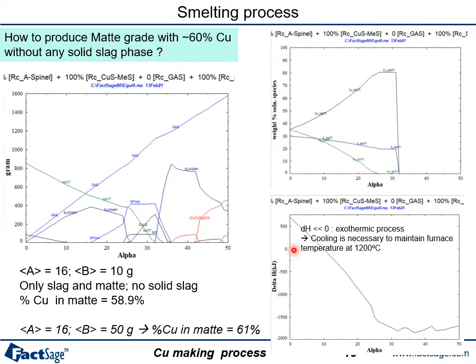So as you can see, this is 0, okay? So again, about this area, you'll have the endothermic reaction, but after this one, you'll have exothermic reaction. So when you see from 10 to about 16, it is all negative value. So it means you have the exothermic reaction. And by the way, this is in kilojoules. So this is about a couple of 100 kilojoules. Actually, the energy is produced per around 500 gram of the input.